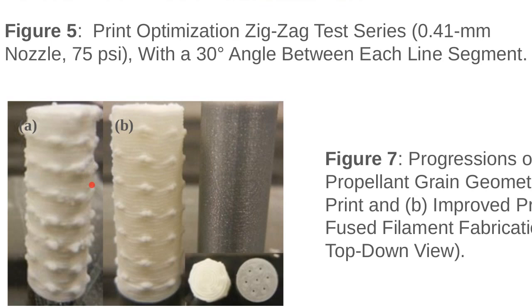But interestingly enough, that allowed us to discover an additional parameter to test in the future, the auger retraction time. The auger retraction time is how long the screw will actually spin backwards in order to retract material after a dispensing command. Unfortunately, we didn't have the opportunity or the time to formally test this parameter and incorporate it into our design of experiments, but with the tests that we were able to run, we did see that increasing the retraction time reduced the severity of those bumps, and we're able to get what Jorge is currently pointing to, a drastic difference between A and B bumps.